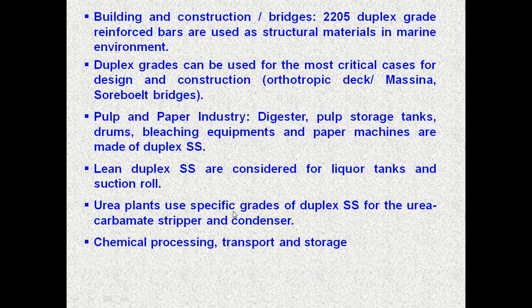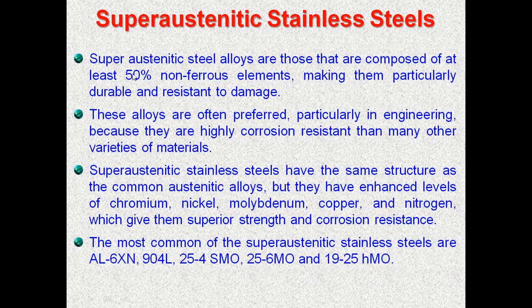And urea plants use specific grades of duplex for the urea carbamate stripper and condenser. And most of the chemical processing, transport, and storage, where high temperature is not involved and most welding is not used, mostly duplex are used as pipes and tubes and so on, because there is not much welding and high temperature involved. The superaustenitic stainless steels are those containing more than 50% of non-ferrous elements, like the chromium, nickel, and molybdenum. If you add, that is more than 50%. The rest is only iron.